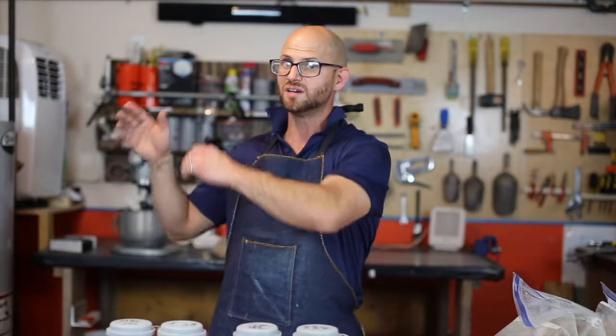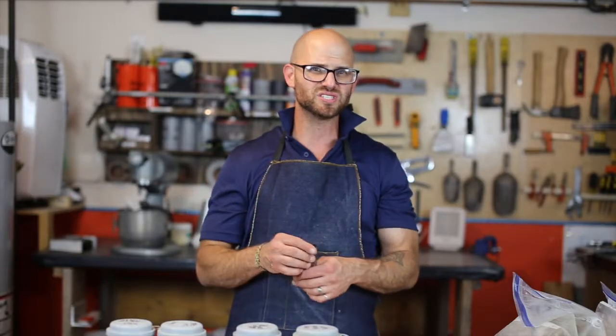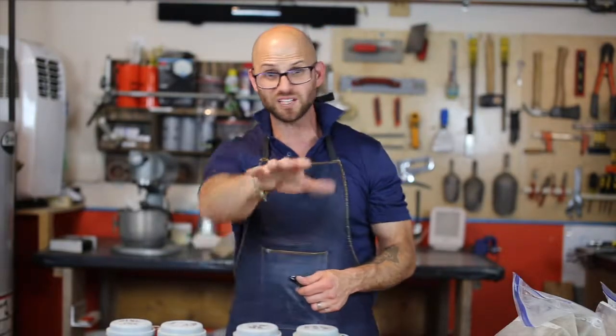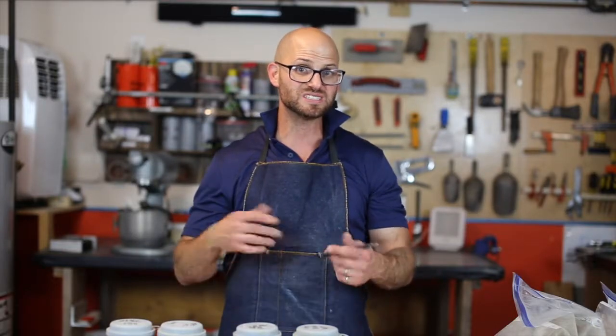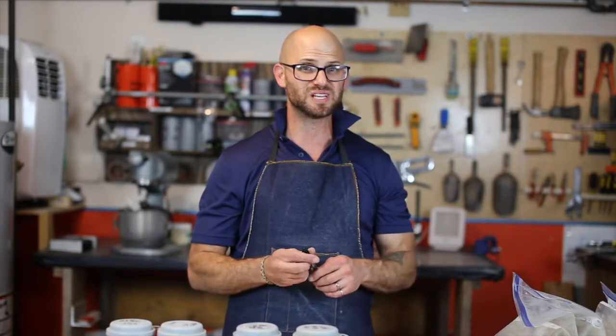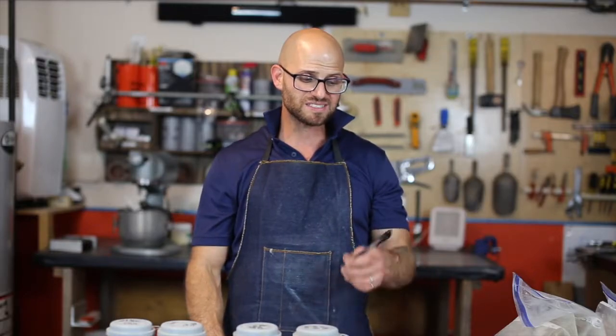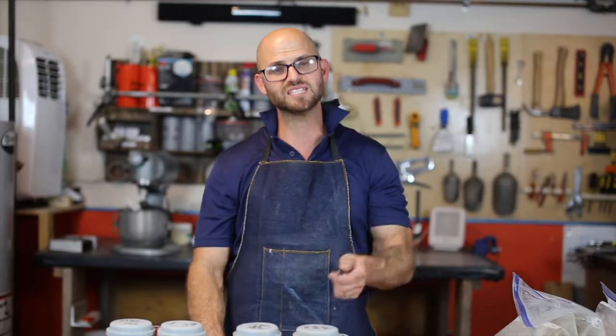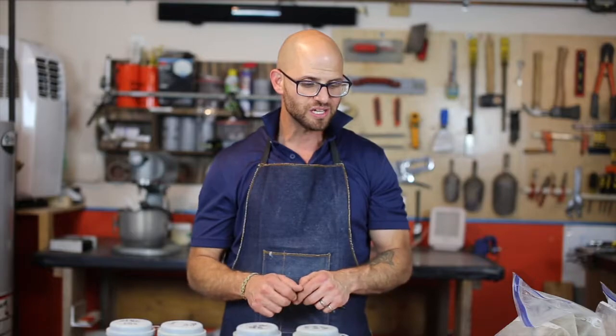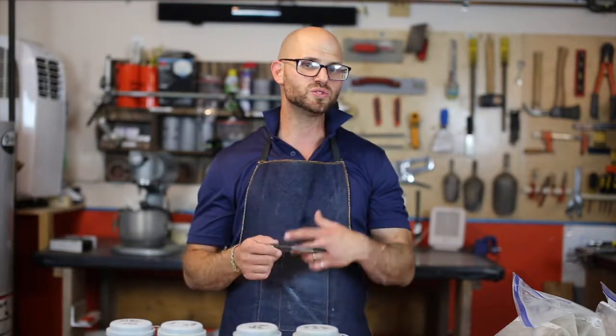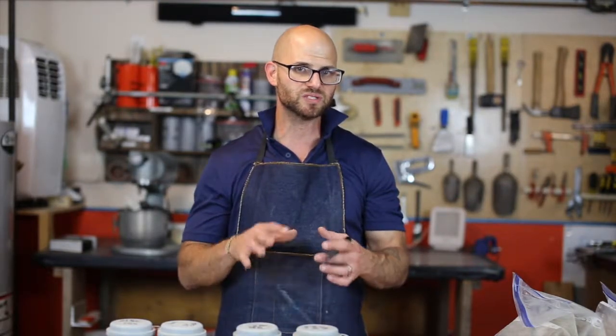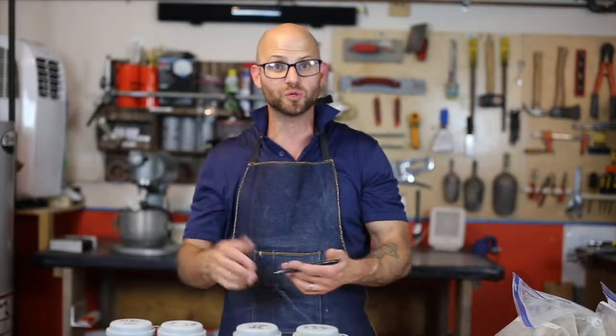Now bear in mind, with the 1101, I think we got a little bit shy of 5,000 or a little bit over 5,000, which is great. That was at 28 days. We wanted to see if we can reach that ultimate strength in 7 days with the bells and whistles that we added. We also added 10 mils of a densification agent and nanotechnology, which again was used to densify the hydrated cement matrix, that porous sponge that makes up the concrete, to give us more strengths. And that coupled with that non-chloride accelerator, we should see even more early strengths.